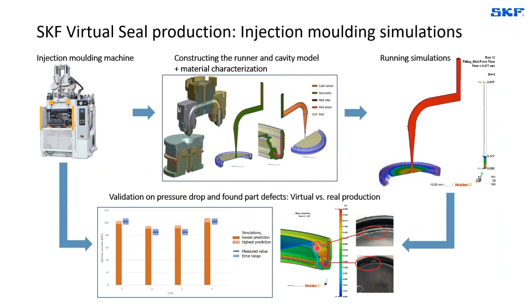And here I'm showing an example of how we can compare the simulation results versus the actual experiments, where we can see the good agreement between the different regions where defects were expected based on the virtual seal production and were in fact observed in reality. Here I'm also depicting the correspondence over a validation that we carried out for our tools for injection molding between the experimental data here in blue versus the prediction for our SKF seal virtual production. And I think we can agree that over a number of cases, they are in quite good agreement.